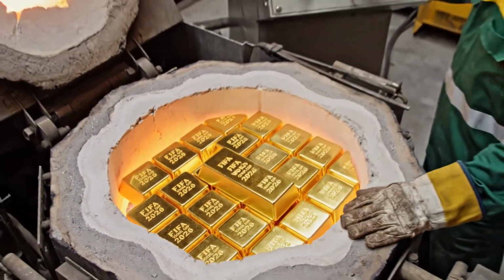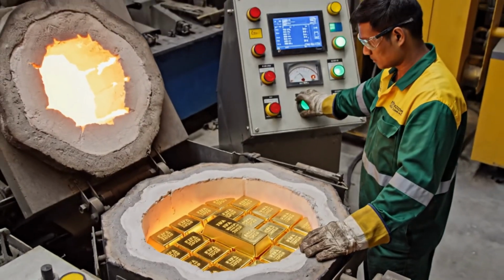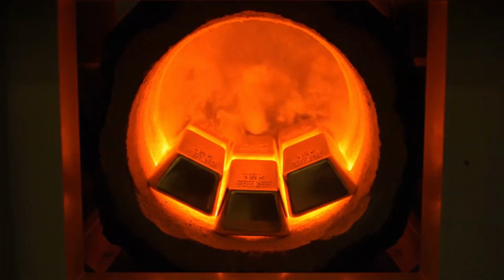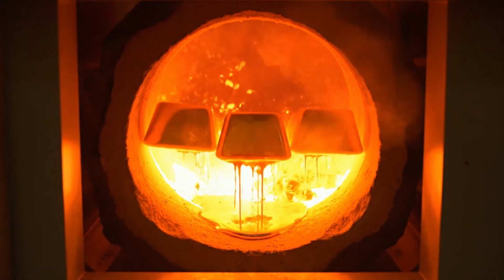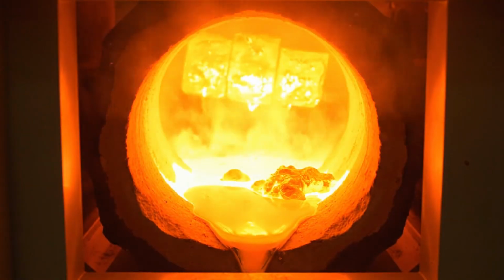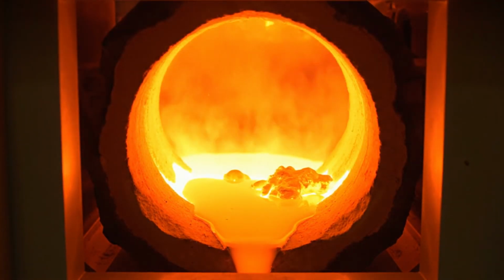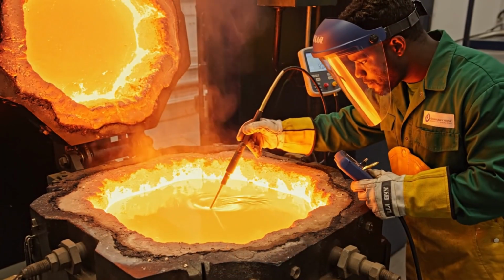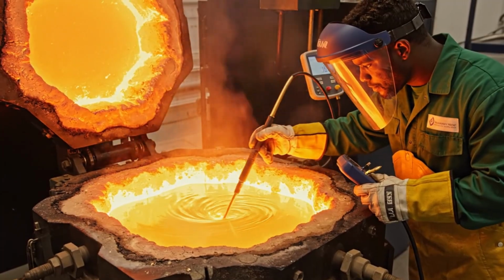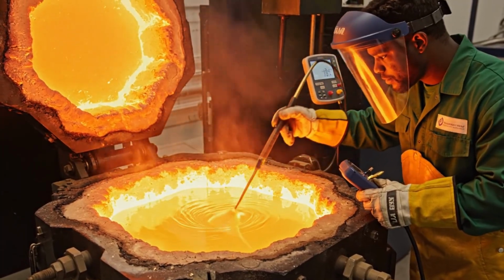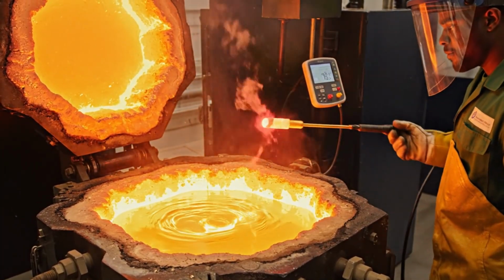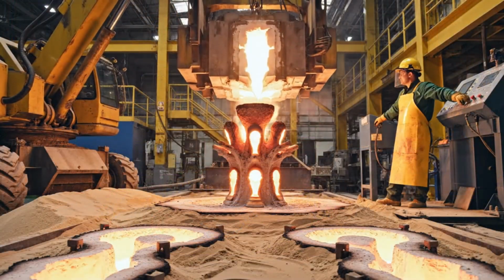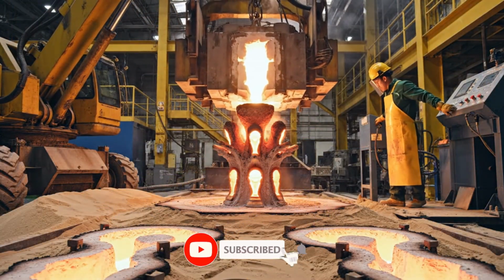To cast the $20 million gold icon, precision is key. The 18K gold bars begin to slump and fuse, turning a bright orange as they partially liquefy. Soon, inside the furnace is $20 million worth of 18-karat molten gold. The alignment must be perfect before the pour begins.